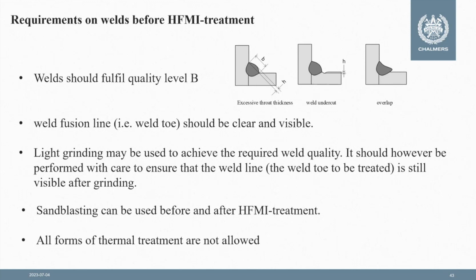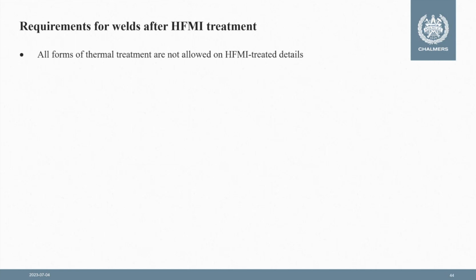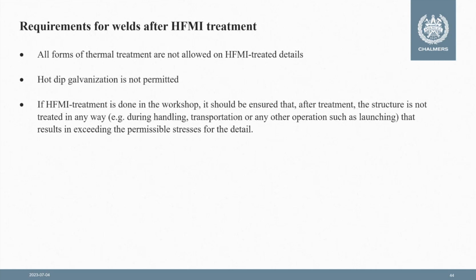However, all forms of thermal treatment are not allowed, both before and, of course, after HFMI treatment, because they affect both the microstructure of steel, but also the residual stresses and their distribution, and they result in relaxation of residual stresses. After HFMI weld treatment, again, all forms of thermal treatment are not permitted. Hot dip galvanization is, of course, not permitted.